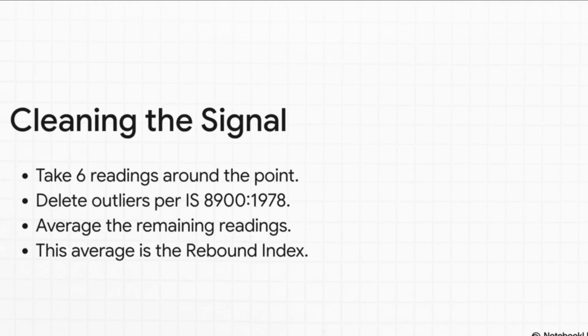You don't just take those 6 readings and blindly average them together. Doing that would pull your data toward any extreme spikes or dips. Instead, the standard demands that you identify and strictly delete outlying anomalous observations based on a separate standard, IS 8900-1978. That standard relies on strict statistical deviation thresholds. So only after you've thrown out the statistical outliers do you actually average the remaining consistent readings. And it's that cleaned, mathematically sound average that officially becomes your final rebound index for that specific point.